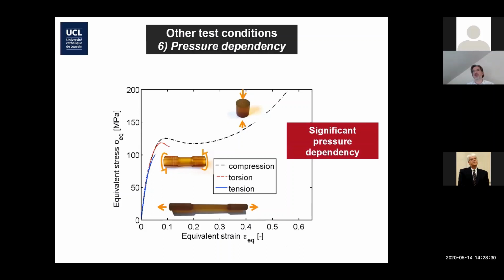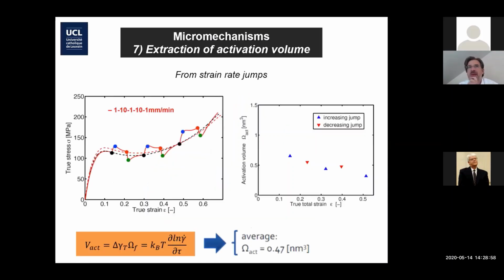Now, typical results known for a very long time on polymers, of course, is the effect of the stress state that is applied on the plasticity. So you get a compression curve here, a torsion, and a tensile test. Unfortunately, the tensile test breaks before getting full plasticity, but you clearly see that there is an effect of pressure dependency, which is well known.